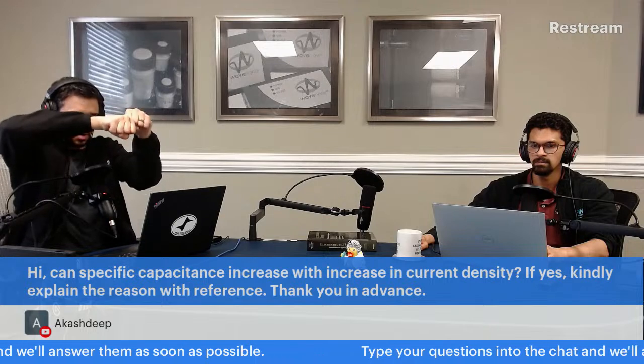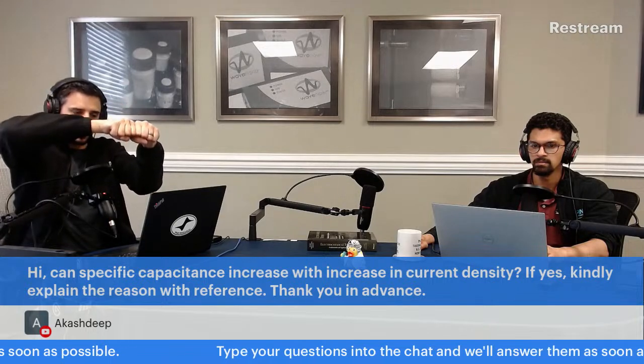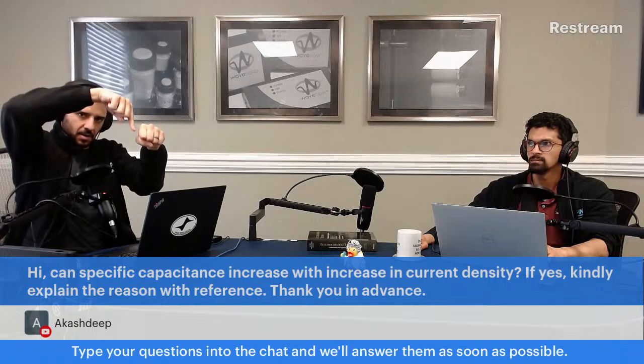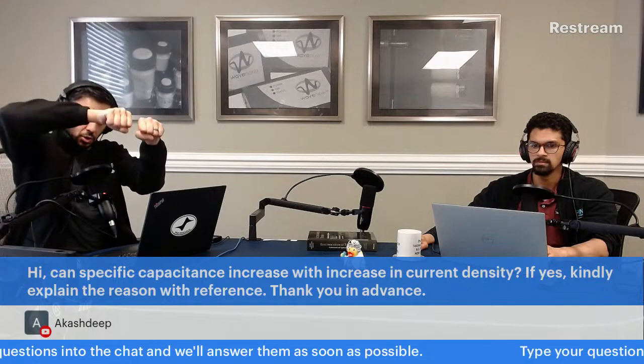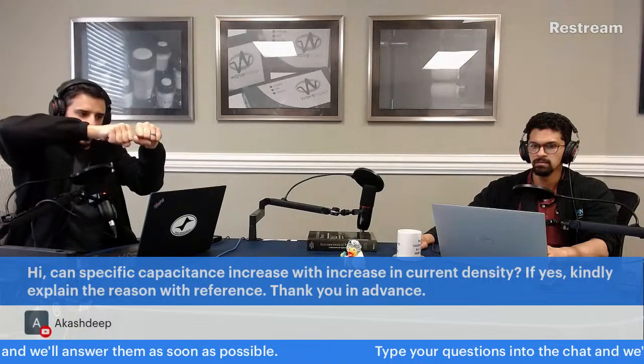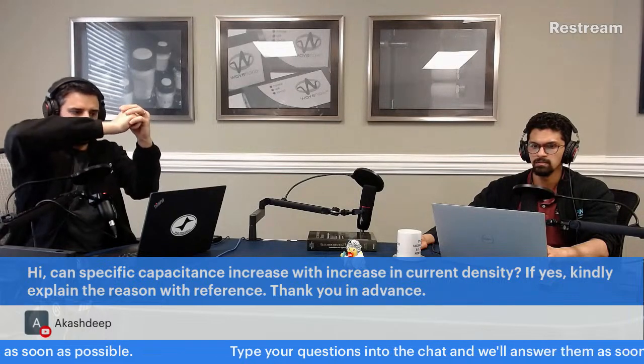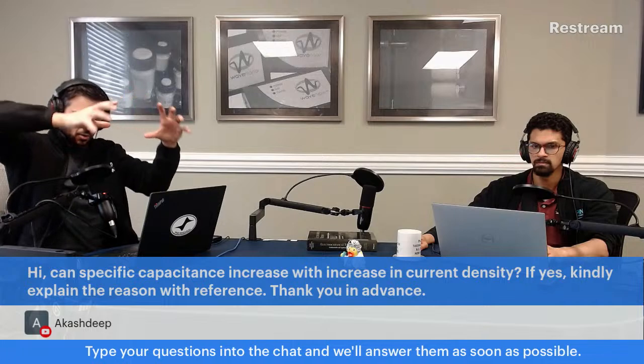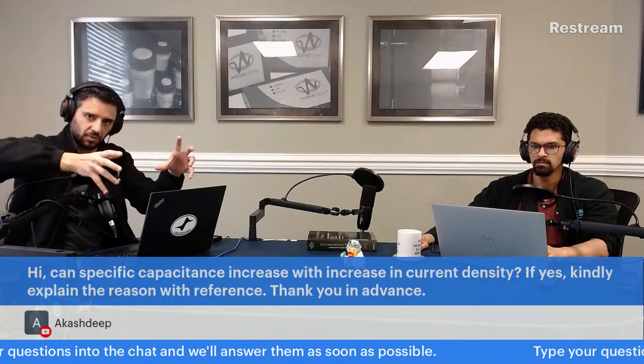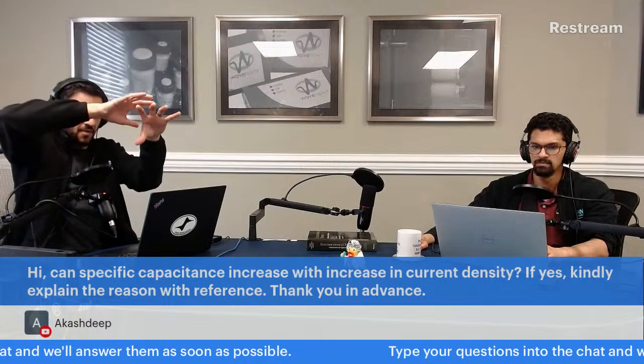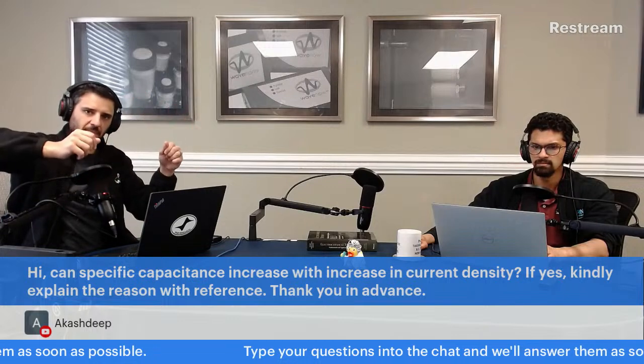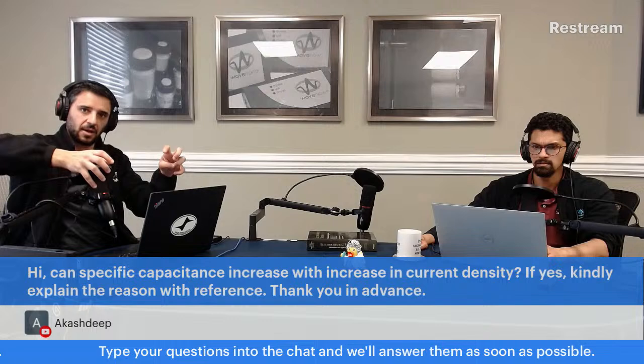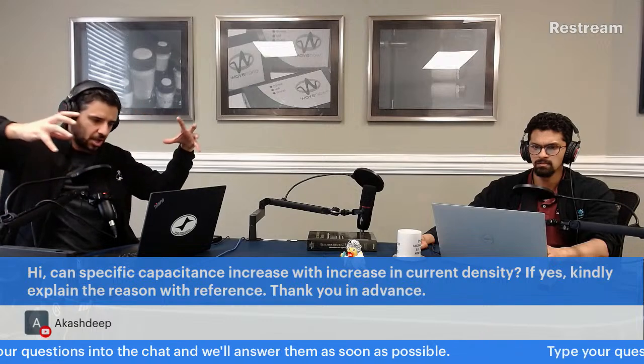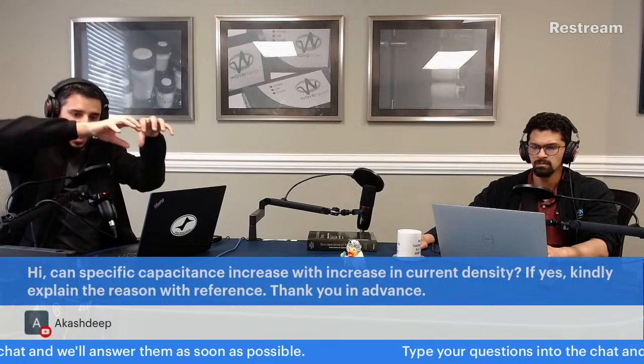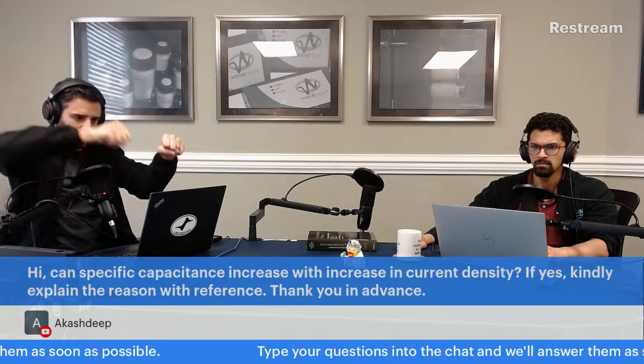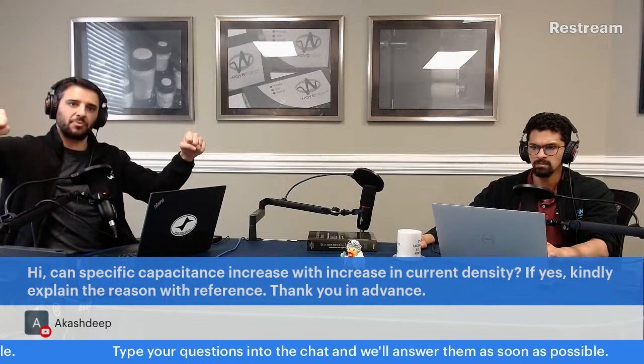They're all next to each other, right? Well, now two spheres that are next to each other, I can't get into the space in between the two. I'm losing surface area. And what if the materials start to grow together and they make a big giant orb? They grow and they coalesce. It's called Ostwald ripening. They get bigger. So I have a big sphere. I've increased my mass, but I've actually decreased the surface area because now my material is glomming on together and I have less available area than if I just had individual orbs all happy and separate.